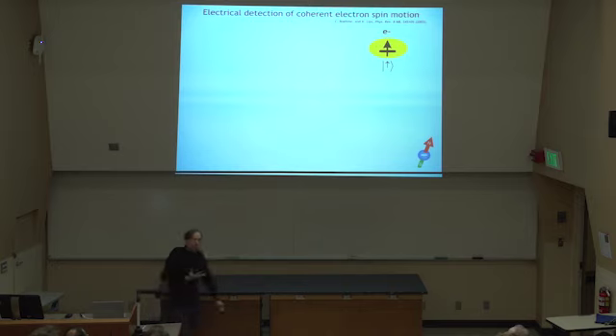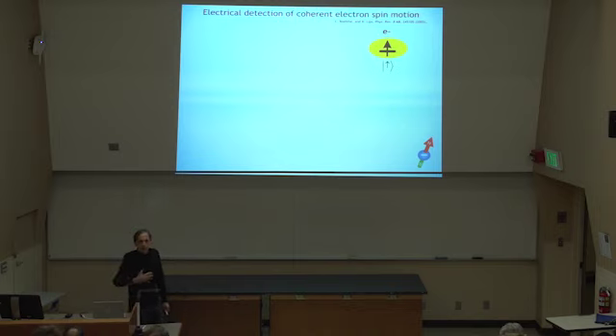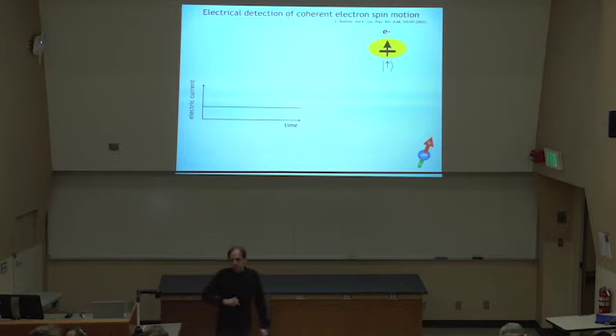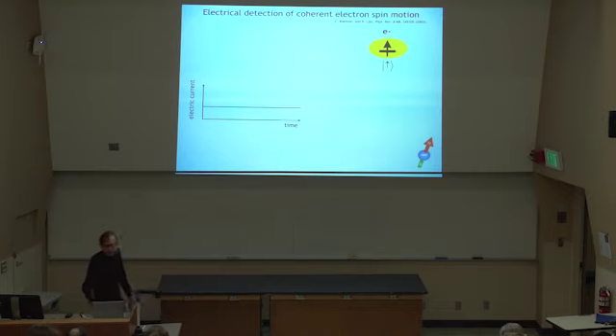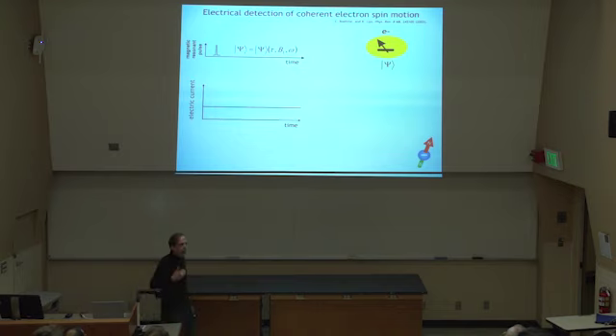Very good. So let's take the naive approach. If we suspect that spin manifolds control electronic transition rates, that's my spin manifold, then we just observe the electronic transition rate, and let's say for the examples that I gave you earlier, an electric current, and measure this. And what we actually did is exactly this as a function of time. And then we start to manipulate our spin manifold, hopefully in the most controlled and most accurate way. That actually means, in our case, we do this with coherent excitation. So we used pulsed electron paramagnetic resonance excitations, but not as a spectroscopy per se, really just as a coherent manipulation tool.